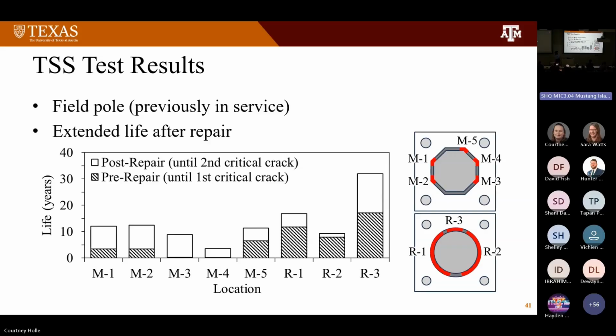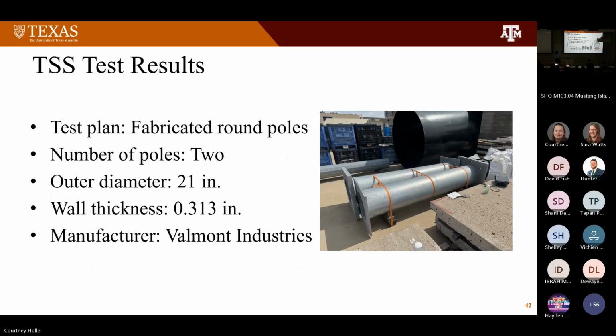About these clear sections, the post-repair life, you may see the variation in this post-repair life. It is from 1 to 15 years, but it was largely due to the differences in welding parameters in the repair process. At the time, we were refining our welding techniques, including welding speed, welding rods, or welding amperes to achieve a consistent result. But even with this variation, it is clear that repair can extend the fatigue life.